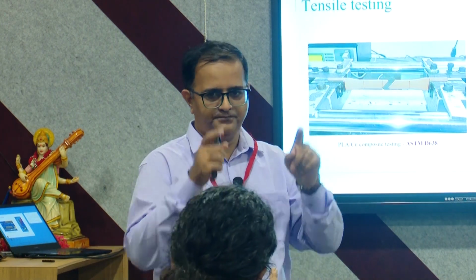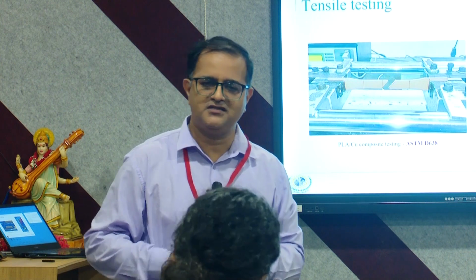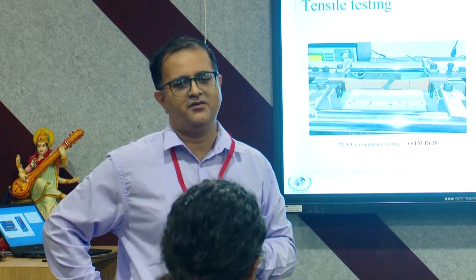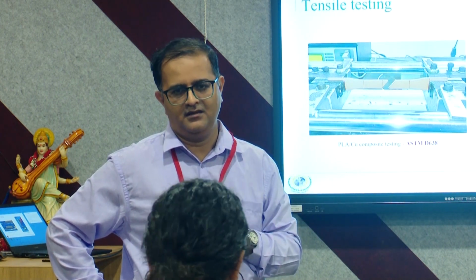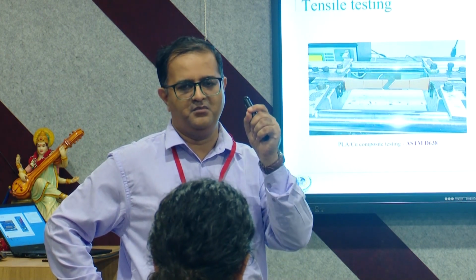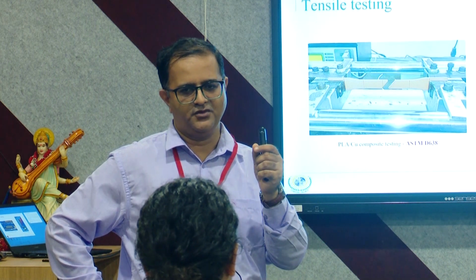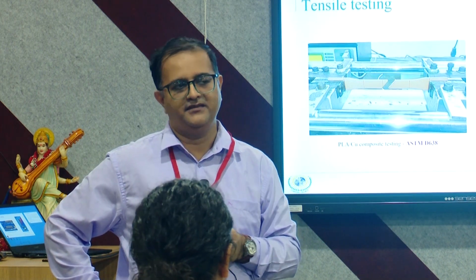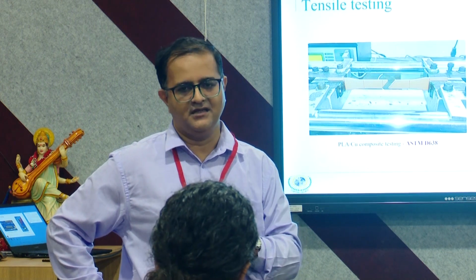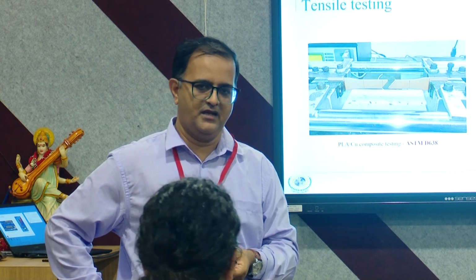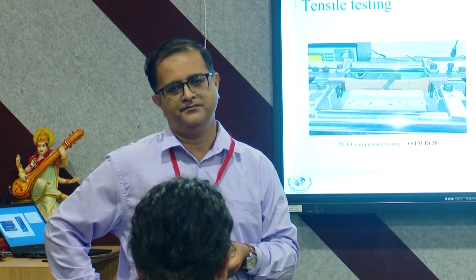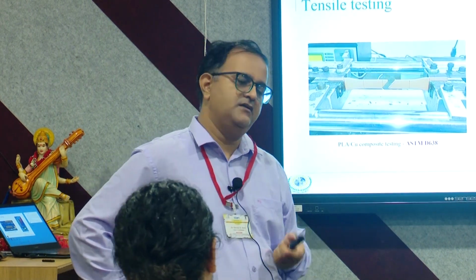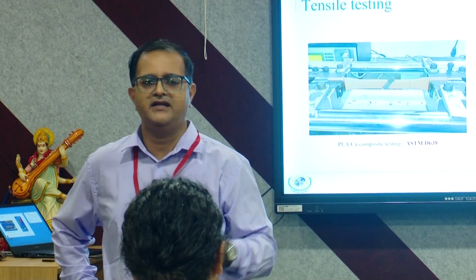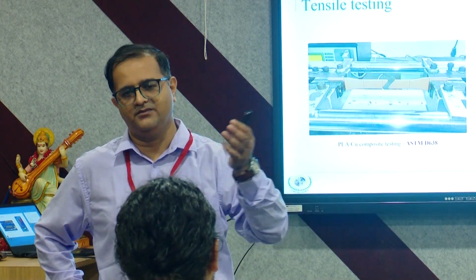These are cut by abrasive water jet machining. Laser was an option, but what we observed was that at the edges those fibers were burning. It was turning black on the edge and those portions were getting burnt. The other thing we observed was that because this is resin, the resin also burns and creates a foul smell. So we avoided that, and that was one of the reasons. The other reason was that the machine was available with us at that time. So that was a better choice.